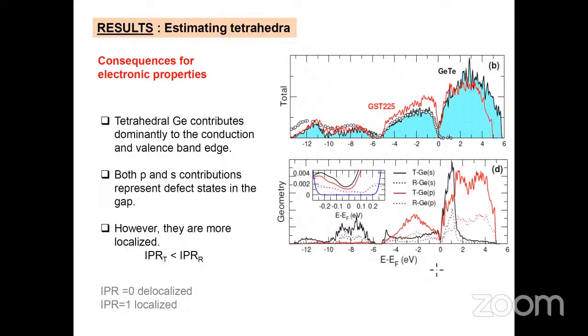Furthermore, we also see that these contributions represent an increased defect state in the gap. In blue, you can see the calculated crystalline gap, and here the solid line is the one arising from the S or P band of tetrahedral germanium. This is the residual germanium, which is much closer to the calculation for the crystalline electronic density of states.